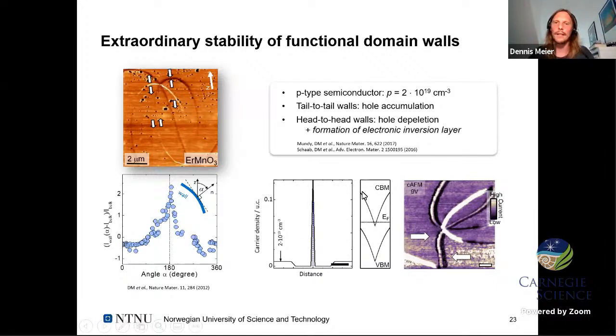What can happen is that because of the depletion, the conduction band minimum that's shown down here dips below the Fermi energy. And in that case, we have then again an increase in conductance, because locally there's an inversion layer forming of electrons which are sitting there. So when you look at the carrier density and you go towards the wall, it first decreases due to the depletion, where we dip below the Fermi energy. We have enhanced conductance, and you can even see that in local transport measurements.